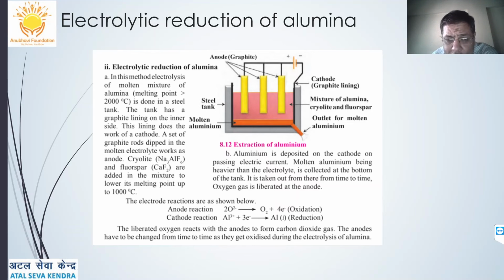And we are mixing the pure alumina with cryolite, that is Na3AlF6, and fluorspar, that is calcium fluoride CaF2, which are added to the mixture, because of which the melting point reduces to 1000 degrees centigrade instead of 2000 degrees centigrade. So we are mixing them because it will reduce the melting point, and also it will save time and energy. Therefore these are mixed with the pure alumina: cryolite and fluorspar.